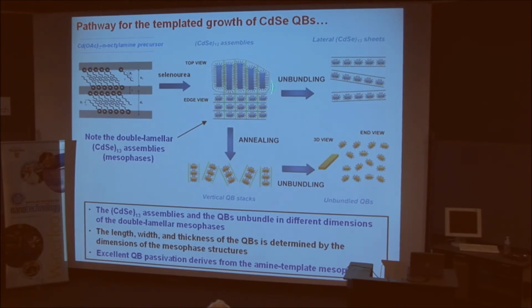If we unbundle these structures at this point, they unbundle in a direction normal to the z direction to give us these individual sheets. If we anneal them, the CdSe 13 nanoclusters recrystallize to form belts that have geometries that are determined by these domain sizes, and they fall apart in a direction normal to the y direction. And finally, we can completely unbundle them to individual nanostructures in that way. So the length, the width, and the thickness of these quantum belts is determined by the dimensions within this mesophase lamellar template.